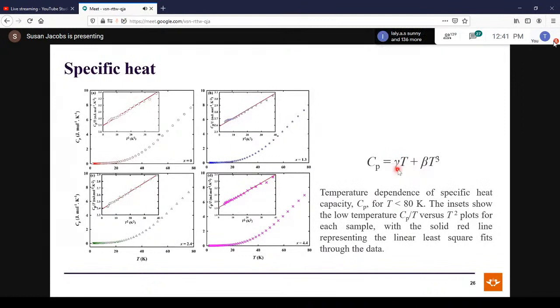So gamma is the Sommerfeld coefficient. The insets over here show the low temperature Cp over T versus T squared data for representative samples. Again, we fit a straight line and the intercept gives us the value of the Sommerfeld coefficient, gamma.